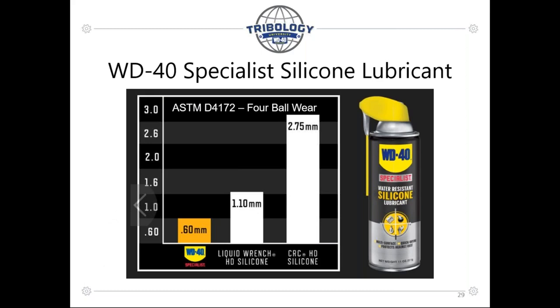And just to give you an idea of performance and how we design our products, when we were coming out with our specialist silicone, we tested it against some of the leading competitors in the marketplace on the four ball wear test. This is the test that determines how great your product is at anti-wear, so a smaller score is better. You can see the difference, right? A 2.75 millimeter scar is probably not protecting your surfaces very well. But 0.6, I could say, is a great score, and that's an area that we're proud of. We test our products, and if they're not the best they could be, we go back to the drawing board. I just wanted to give you a sense of security, knowing that the products we develop have a great sense of performance to them.